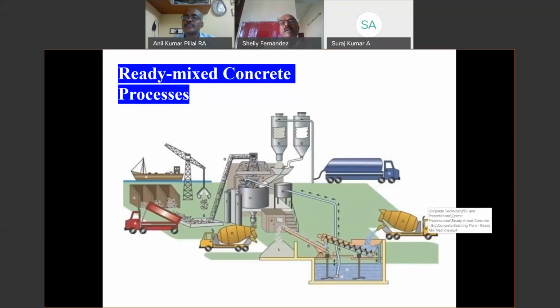Now, I'll briefly describe the ready-mix process. All the raw materials, after being checked, are dumped into the bins. You can see the bins here. On the top of each plant we have 4 different bins, with partitions, for 20 mm, 12 mm, then M sand, and any other material to be used, maybe copper slag. Then we have the water tank, with pure, tested water, which is pumped into the pan mixers. Then we have the mixers being used. Then we have the cement bulkers unloading cement into the silo, where we use an air compressor to pump the cement into the silos.